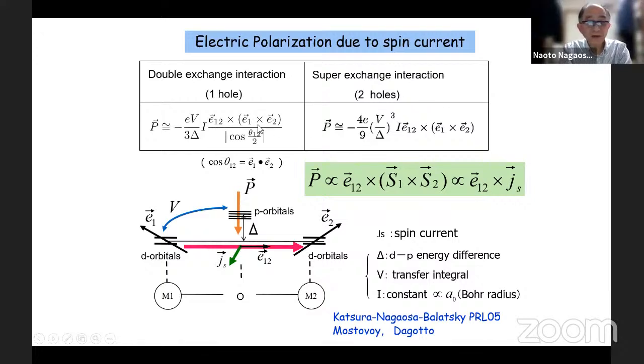And for both of them, we have a typical form of e12 cross e1 cross e2. So e12 is a unit vector connecting site one and site two, right? So then this formula gives a very concise and compact form of the polarization produced by the noncollinear spin structure. So this is a sort of inverse effect of the Dzyaloshinskii-Moriya interaction.